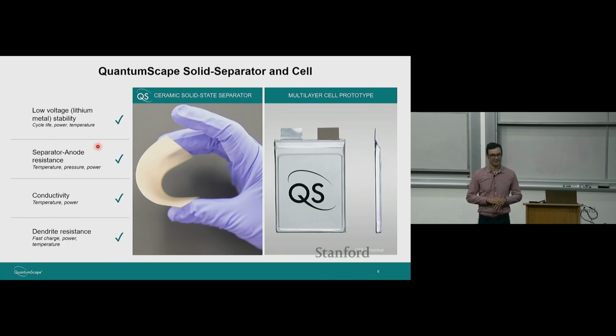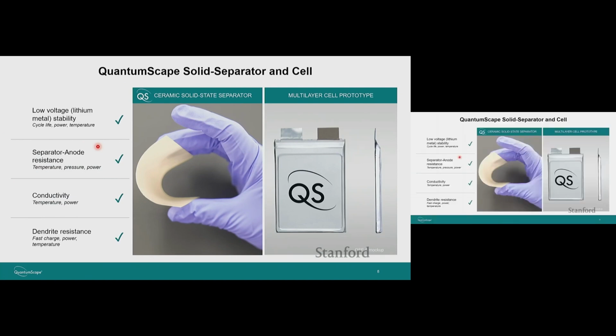This separator has to fulfill 4 key requirements. It has to be stable to lithium metal, as I just mentioned, to enable long life of the battery, also high power across the full temperature operating range. It has to have low resistance to lithium. That means both the conductivity through the bulk of the material as well as at the interface with lithium metal. This may be counterintuitive, but that couple nanometer interface with lithium metal can present more resistance to lithium transport than the entire bulk of the separator.